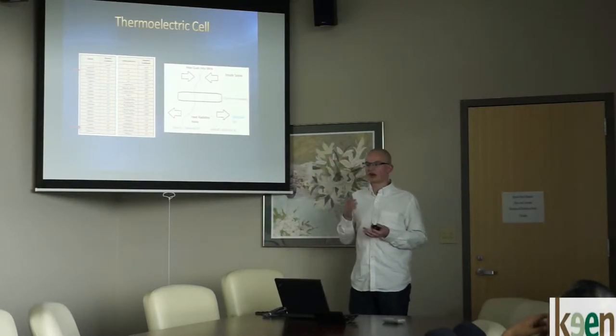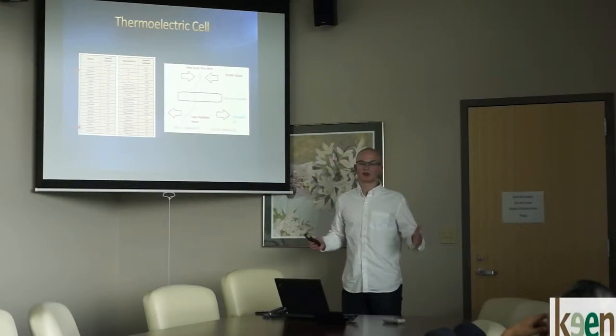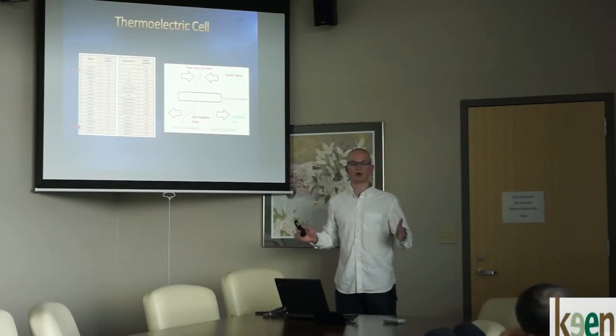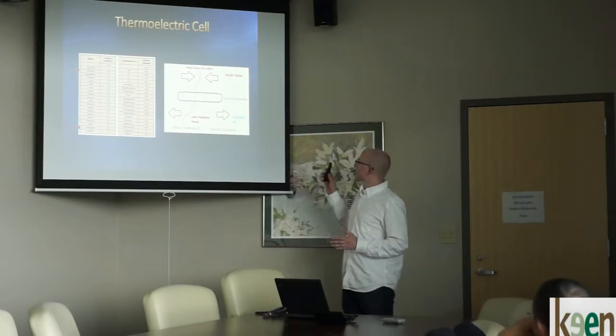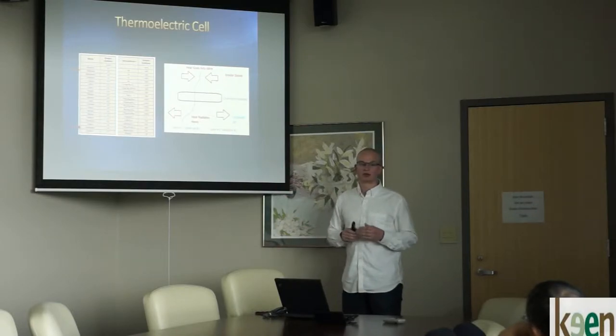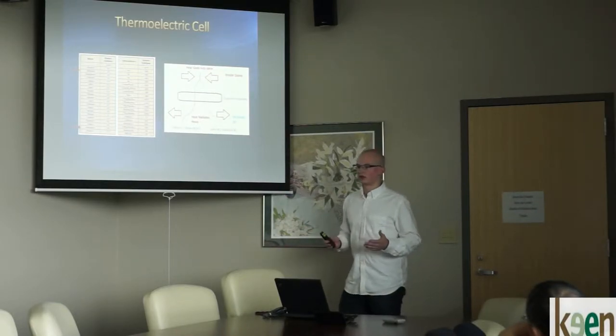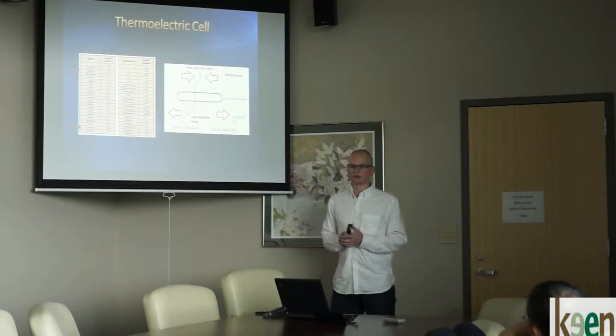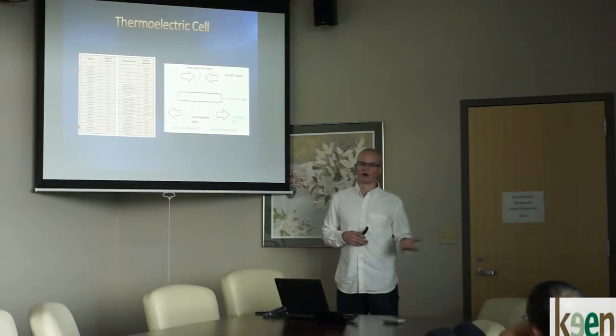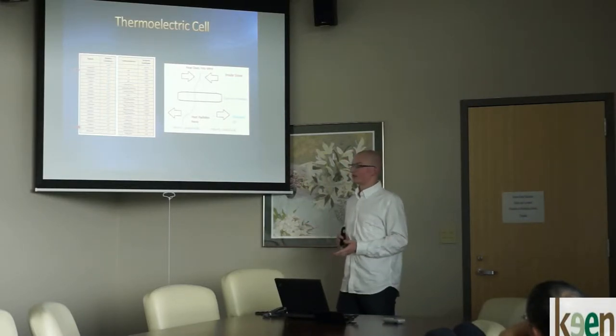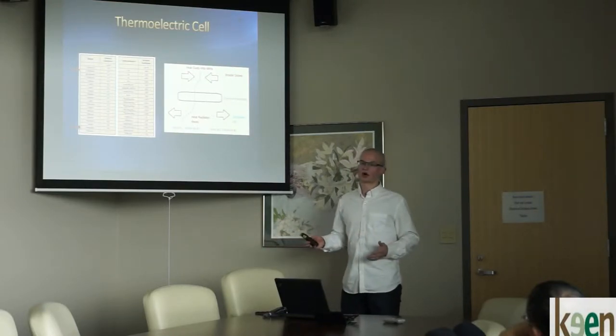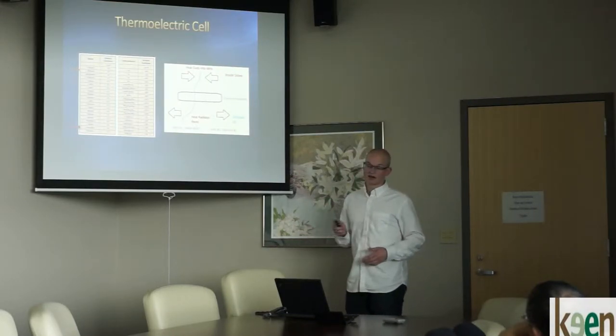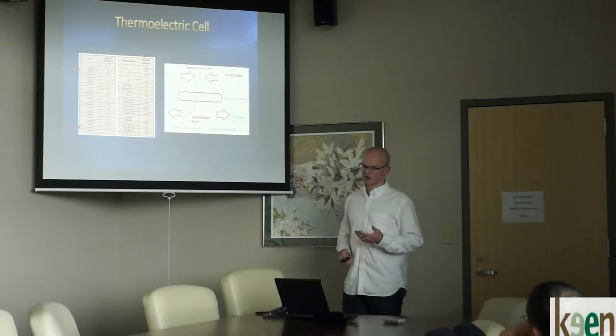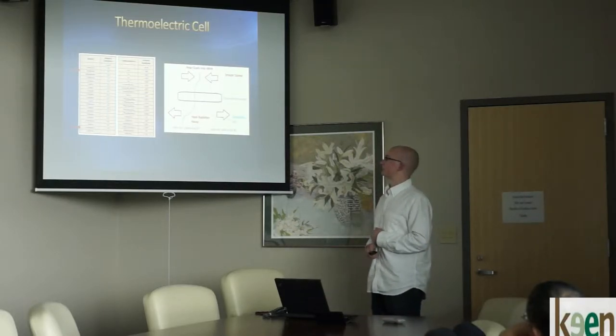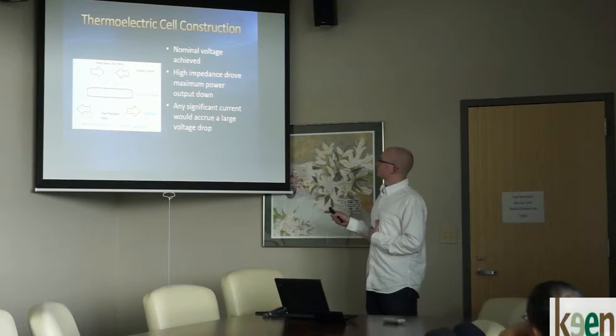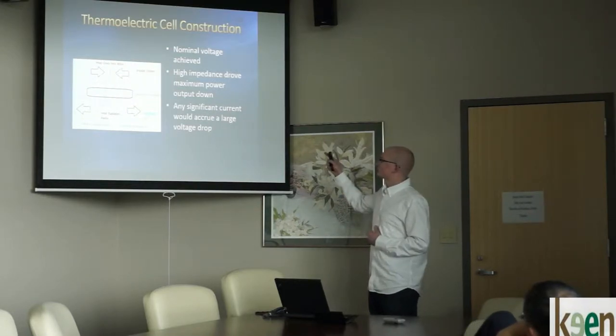I got my voltage. When I did my calculations, I needed about 100 of my cells in series to get a usable voltage. The problem was that my impedance was too high. When I measured it, it was on the order of several ohms, and my voltage was on the order of millivolts. If I keep stacking in series, that impedance is going to grow as well. As we'll look at later, that's a problem of maximum power transfer that happens with these devices.